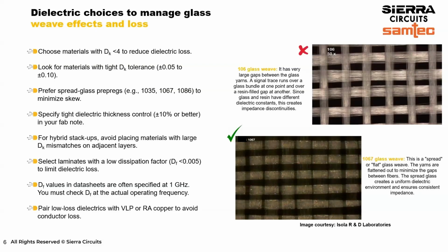For 106 glass weaves, the gaps between glass yarns are large, so the trace keeps moving between the glass and the resin. Since those materials have different dielectric constants, you end up with impedance discontinuities. To fix this, we recommend spread glass prepregs, such as 1035, 1067, or 1086. They use flattened spread yarns that give the trace a much more uniform dielectric environment and keep the impedance consistent.